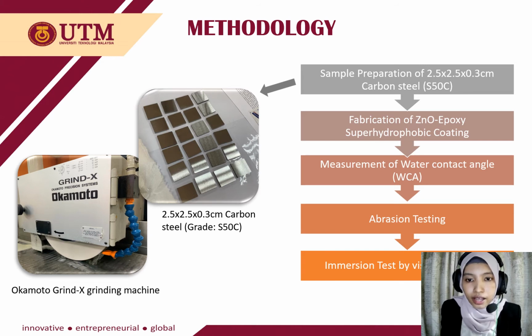And then I fabricated the zinc oxide epoxy superhydrophobic coating in the EMAS lab. However, due to MCO, the pandemic, we couldn't do more experiments. So what we could do is the measurement of water contact angle, the abrasion testing, and the immersion test by visual inspection. We did it at home, as in work from home. We could have done more experiments with better results.